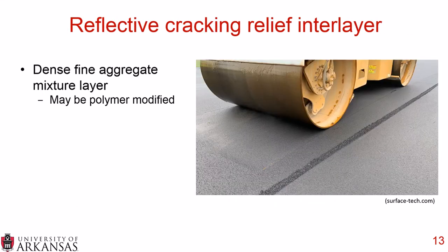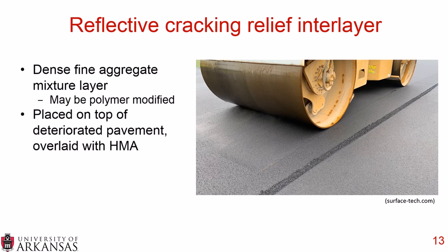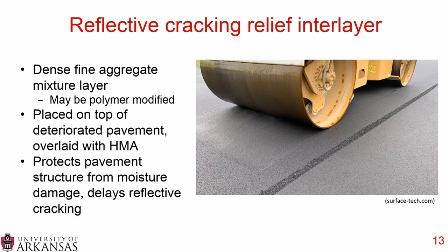And then finally, the third type is a reflective cracking relief interlayer. And this is a dense, fine aggregate mixture layer, and it may or may not be polymer modified. It's placed on top of a deteriorated pavement, and then you place your hot mix asphalt overlay. And it protects the pavement structure from both moisture damage and it delays reflective cracking.